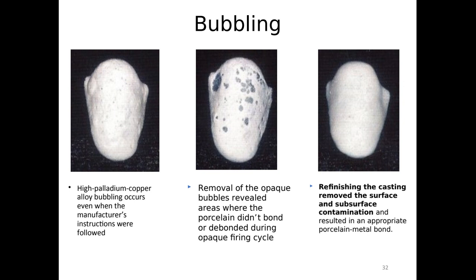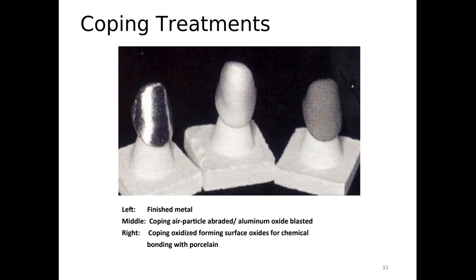High palladium copper alloy bubbling occurs even when the manufacturer instructions were followed. Removal of the opaque bubbles reveals areas where the porcelain didn't bond or debonded during the opaque firing cycle. Refinishing the casting removed the surface contamination and resulted in an appropriate porcelain metal bond. So the coping treatments: on the left we have the finished metal. In the middle is the coping after the sandblasting procedure, and on the right is the coping after the degassing process, when the coping is ready to receive porcelain.